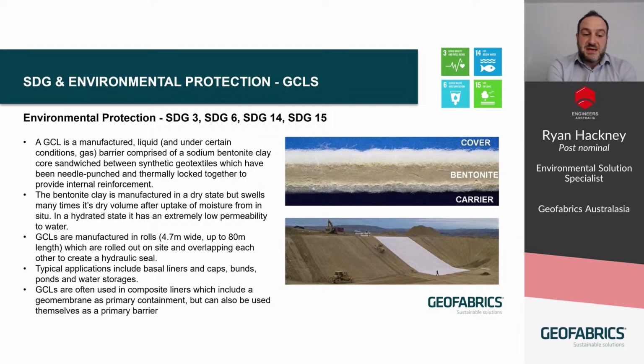That needle punching process provides internal reinforcement to the GCL so that the material is actually stable on slopes, because bentonite alone has a very low shear strength. Bentonite clay is manufactured in a dry state, but it swells to many times its dry volume once it takes up moisture from the surrounding environment. In its hydrated state, and when it's confined, it has an extremely low level of permeability to water, but also to other chemistry, as you'll see in the next slide.